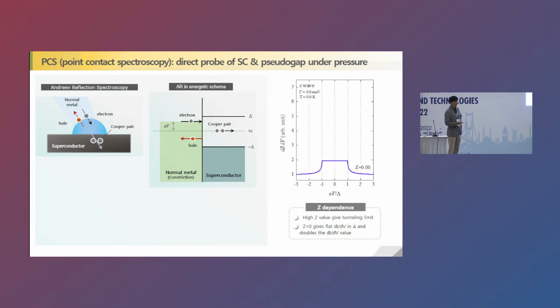However, if there is an interface contact barrier, then you can see that it partially picks up the tunneling. So that's why you have a U-shaped suppression and then the two peak-like features in the differential conductance of point-contact spectroscopy.